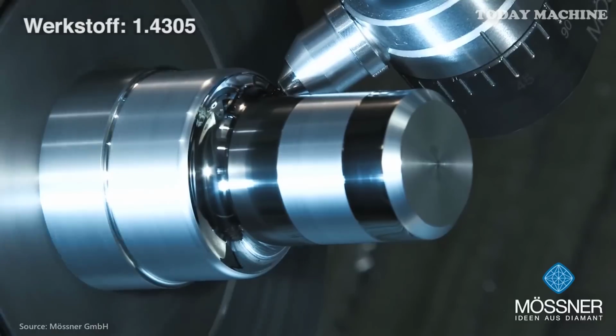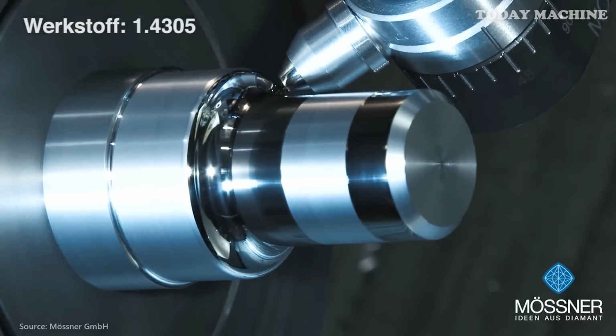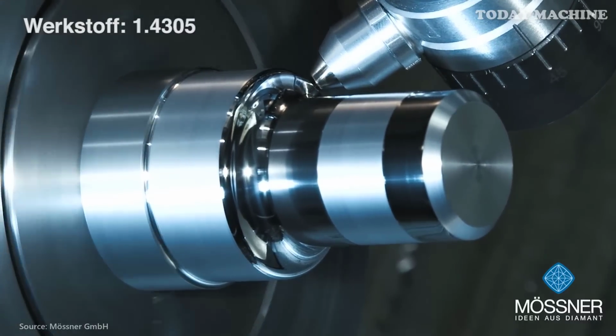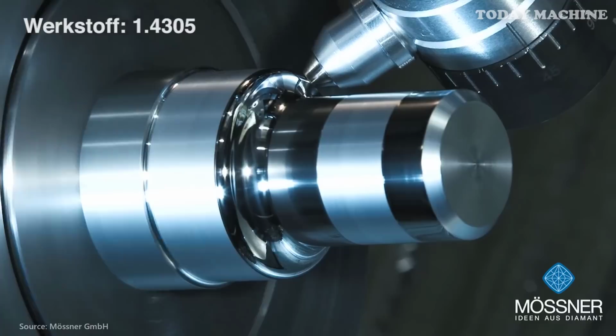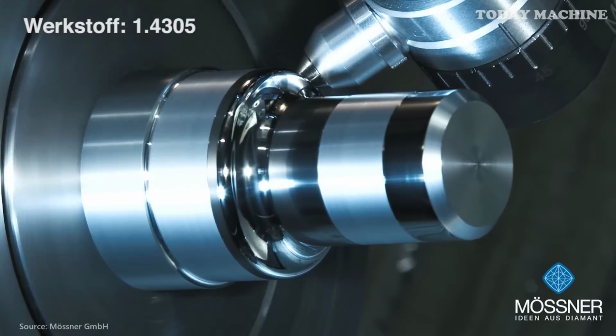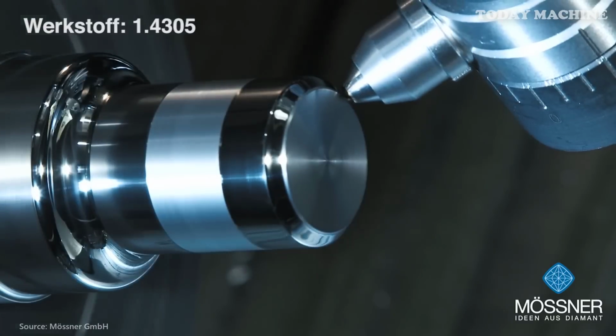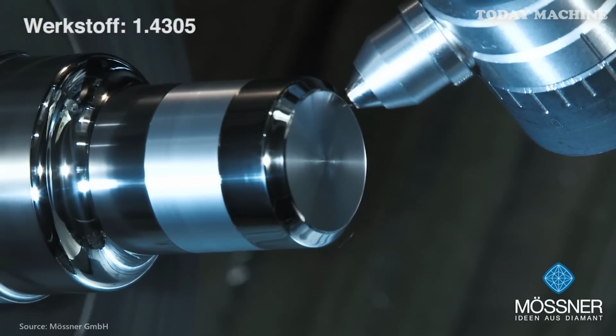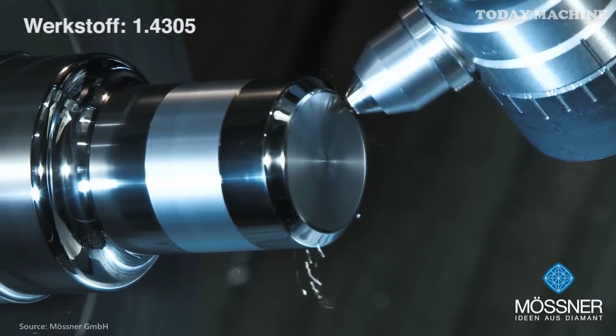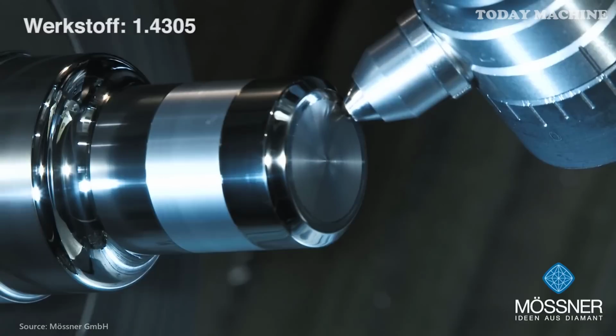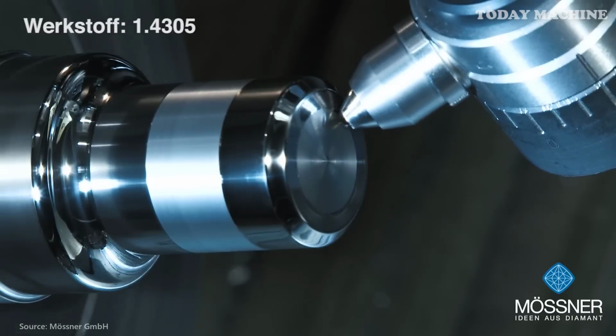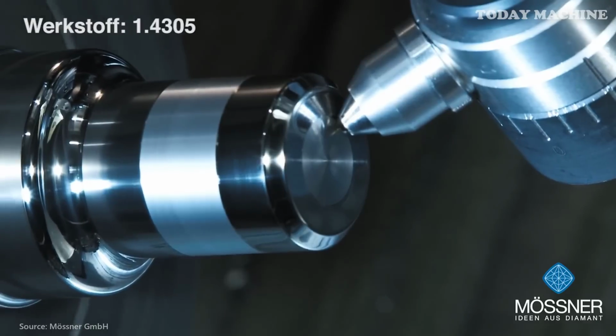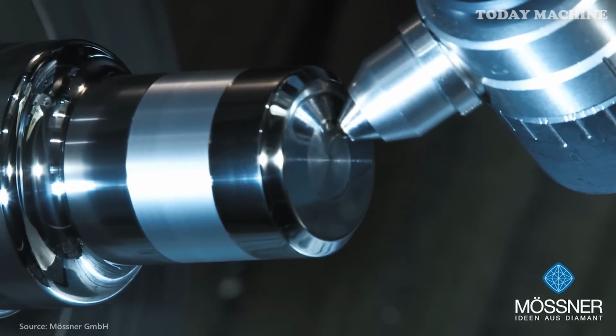To overcome this, the workpiece is first pre-processed using a carbide or CBN, cubic boron nitride, tool. Following this, Mossner diamond burnishers are employed to smooth the surface effectively. This method often eliminates the need for post-polishing, saving considerable time and improving efficiency.